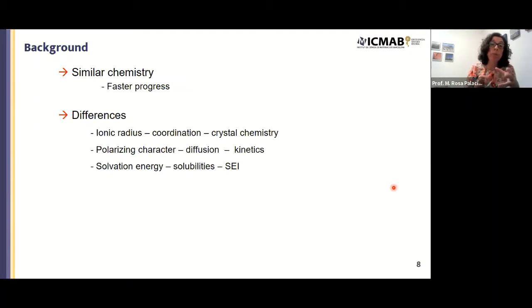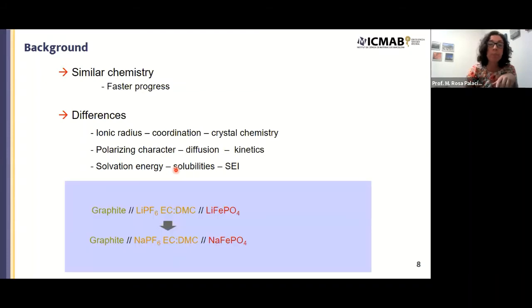Then the polarizing character, as a result of having the same charge but different radius, is also different. This will impact the diffusion and the kinetics. And finally, also the solvation energy. So the solubilities of lithium and sodium salts may be different. And this will impact what is called the SEI, the solid electrolyte interphase, which is a passivation layer built on the surface of the negative electrode, because this is operating at very low potential where the electrolyte is not stable. So the electrolyte decomposes on the surface of the electrode, pretty much protecting it like aluminum oxide protects aluminum from oxidation. But then if these compounds that are formed there are soluble, then the protection really will not work as well.